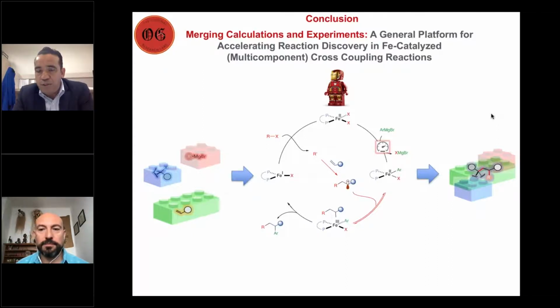I'm not showing those results, but I think those are very exciting, where the pre-catalyst, like you mentioned, might generate different species in situ. And when you have a chiral ligand, that might generate a wide range of different iron species that might lead to unselective transformations. What you want to do is really have a more controlled system where you generate only 1 or 2 different iron species, one that could engage in generating the radical, and the other one that could trap the radical. If you're able to do that, then that will lead you to more selective transformations.